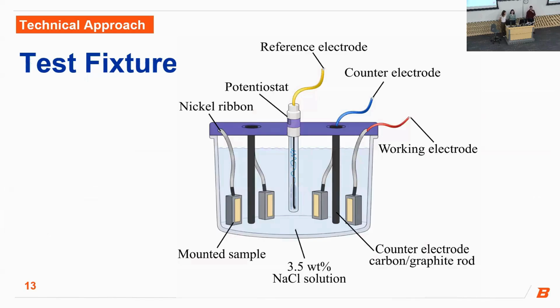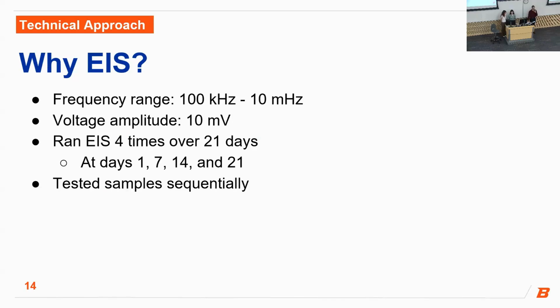All of the samples described were tested using this setup depicted in the slide. Our samples were submerged in 3.5 weight percent NaCl solution to mimic seawater inside a plastic container. The lid had holes in it to hold the reference electrode and the counter electrodes in place. The samples were submerged in solution for about an hour before the first EIS test to allow for the corrosion potential of the samples to stabilize. The samples sat in solution for a total of 500 hours, which is equivalent to 21 days. EIS was run 4 times over the course of 21 days at days 1, 7, 14, and 21. This was to monitor the corrosion behavior over the course of exposure.